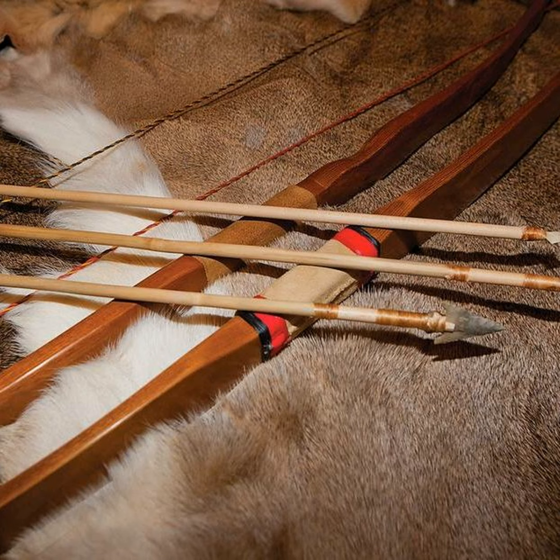If I look at Osage orange, the modulus of rupture, the bending strength, is 18,650 pounds per square inch. The MOE, the stiffness, is 1.7 million pounds per square inch. It's really high. But if you look at those numbers, they can tell you here is kind of the perfect wood, to the point where they actually call it bow wood in parts of the world.